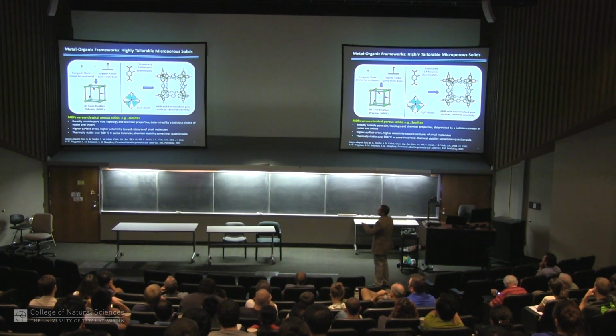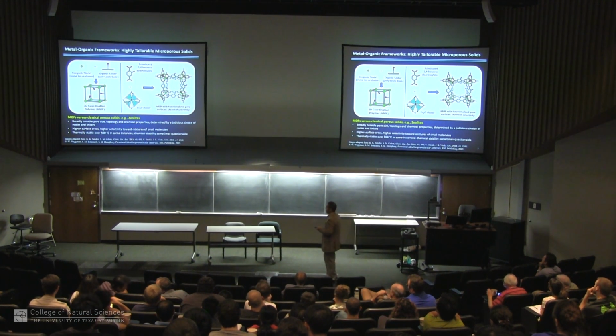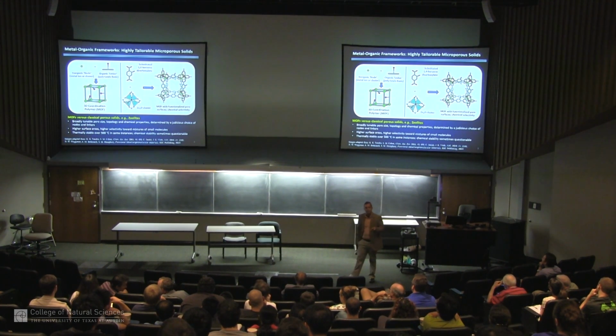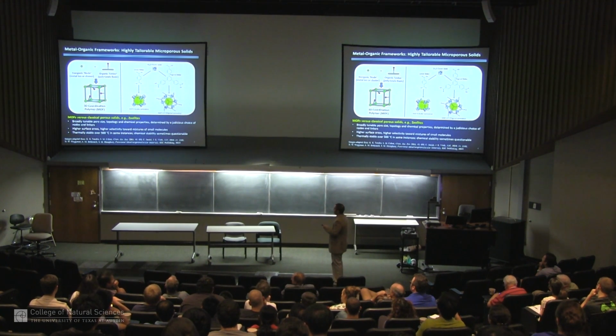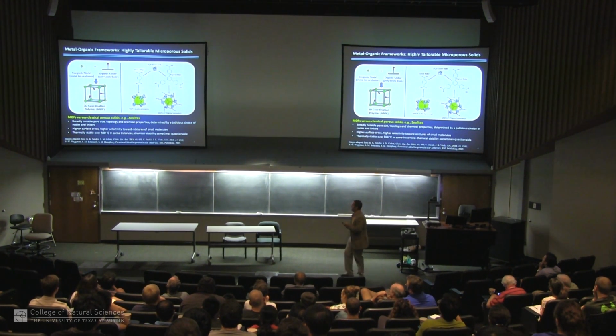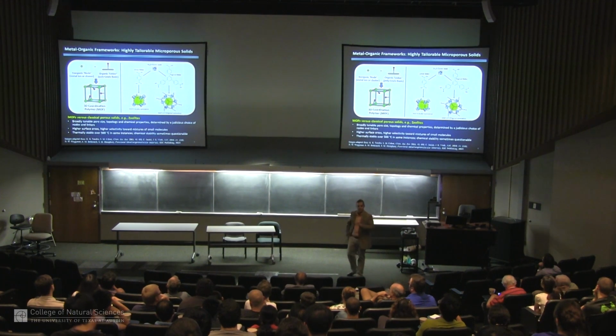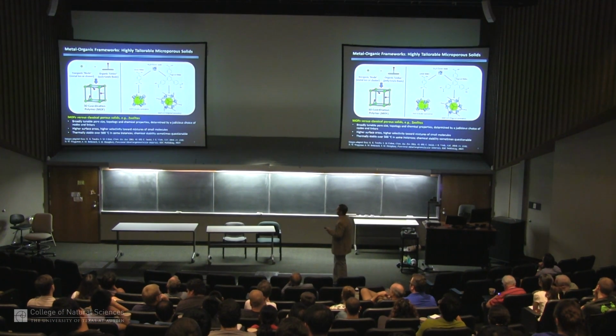And because we're making strong coordination bonds, you can get materials that are thermally stable over 500 degrees. So they're very applicable, and they could be used as replacement technologies in industrial processes, such as separations of molecules and storage of molecules. And also, if we want to change the characteristics of the material, it's a simple approach that means the geometry of the organic linker really ends up being transferred into the geometry of the material. So if you take a linear linker, you get something that looks cubic with the same inorganic nodes. If you take a trigonal linker, you can make something that has trigonal or hexagonal symmetry. So this is how we control and think about how to build these materials.